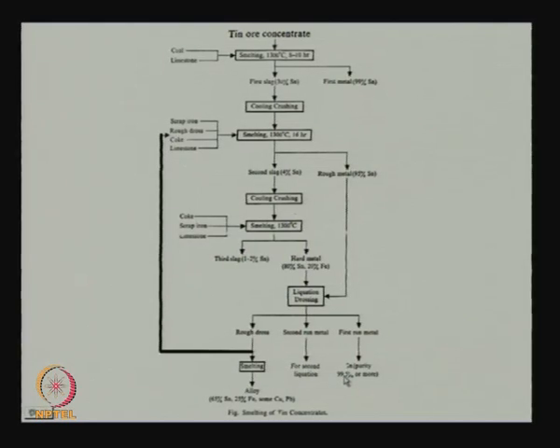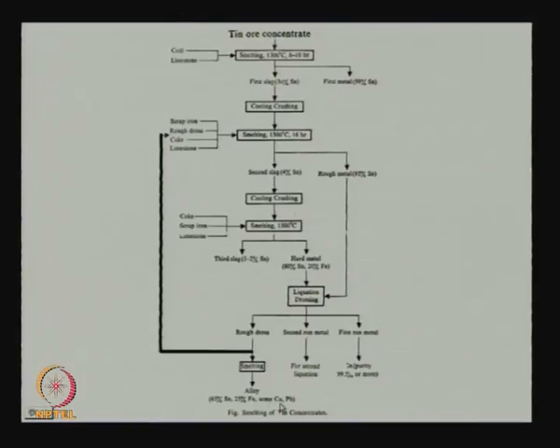But as you take out pure tin, you are changing the composition of what you are purifying. In the second step, it will not be so pure tin. In the third step, it will not be very pure. It will only have 65% tin, it will have 25% iron and copper and lead. This will have to be recirculated back here. So, this is a classic metallurgy of tin, where things are very, very interconnected.